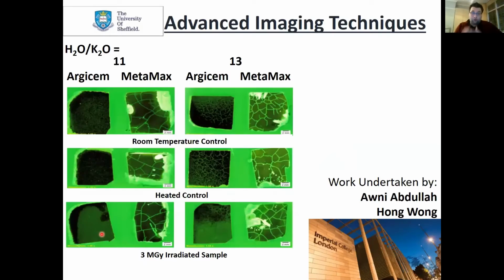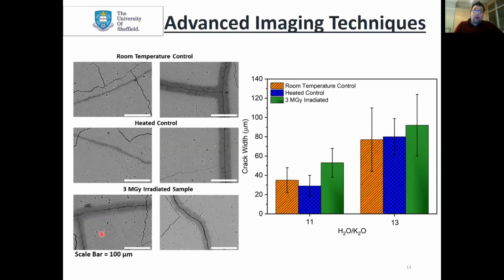If you look at the Argicem sample structure, you'll see it's really covered in quartz and is really heterogeneous, so it's hard to pick this out using this technique. So what we're going to do is just look at the Argicem Metamax rotary calcine product. You can see it's a relatively heterogeneous structure with some pores, and the epoxy has impregnated into these cracks.